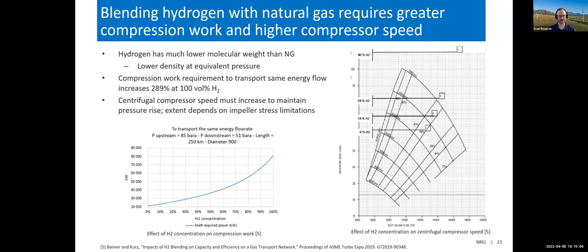So in order to maintain the same pressure rise, they'll need to increase in speed, which could become a limitation because the speed limits on centrifugal compressors are often related to the impeller stress constraints. The extent to which a centrifugal compressor is going to be able to tolerate hydrogen is going to depend a lot on what its overspeed specifications are. In this particular study for this compressor, they found that they could blend about 17 or 18% hydrogen before they hit their maximum speed limit on this compressor.